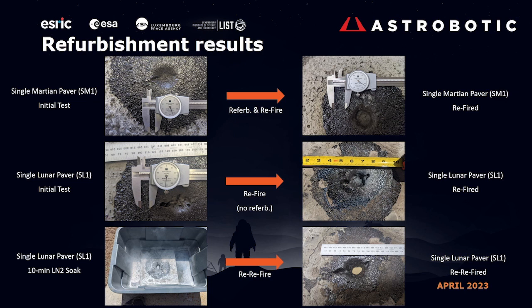And since we had them out there, we had the engine, we had the time, we just kept firing at them. So we did a secondary firing on one of the landing pads after not repairing it, and that pad did hold up. And we had that pad with two fires on it, and we had a bunch of liquid nitrogen from another project sitting nearby. So we decided to soak that pad in liquid nitrogen for 10 minutes and then put it directly under the rocket engine and fire again.